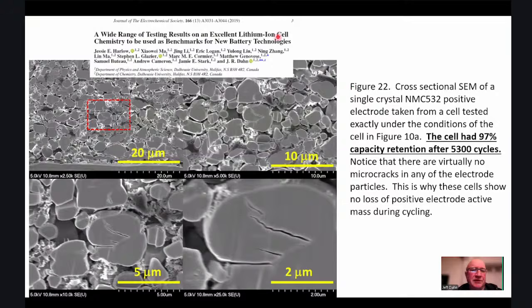And we published this paper in 2019 where we followed cells with single crystal positive electrode materials. And this is an SEM cross-section of the positive electrode. After 5,300 cycles, the cell had 97% capacity retention. And these cells were cycled over 100% depth of discharge for 5,300 cycles. And you can't see very many cracks in these particles at all. If you look at this big one here and here and here, there's some big cracks in it, but they may have been there from the beginning. Who knows?